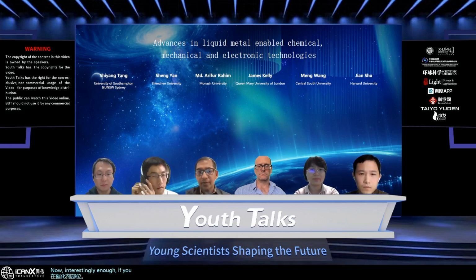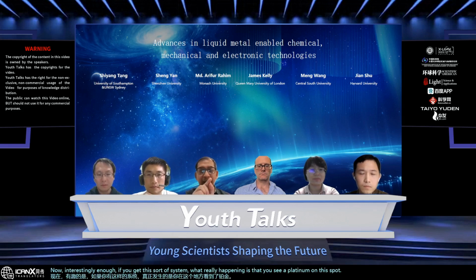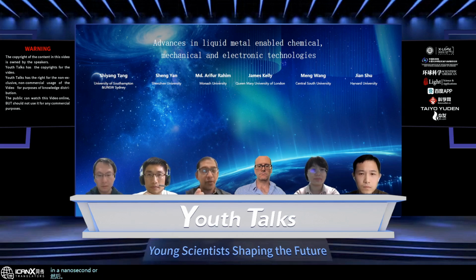Interestingly, if you look at this system, you see a platinum atom on this spot, and in a nanosecond, it's not here anymore. It can go here or it can go down. It's a continuous process. We had a calculation that each platinum atom in gallium was changing its position about 10 to the power 7 times per second, or close to that. This has a serious impact on your kinetics, because every time you are creating almost like a new position, your concentration changes. It is not a precise calculation, just an estimate.